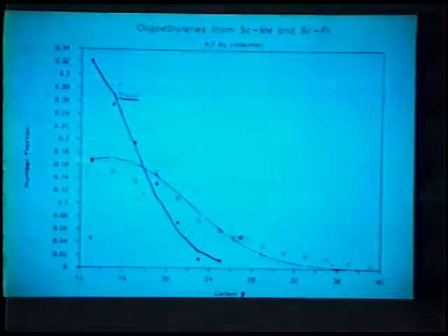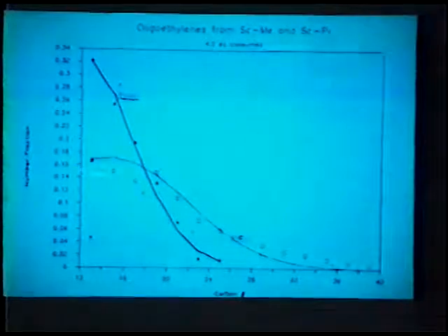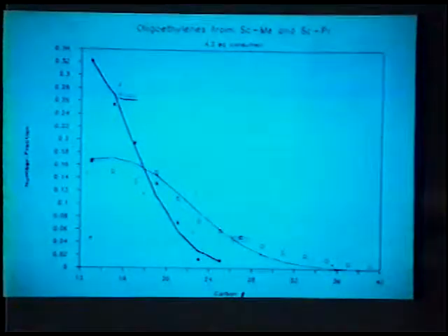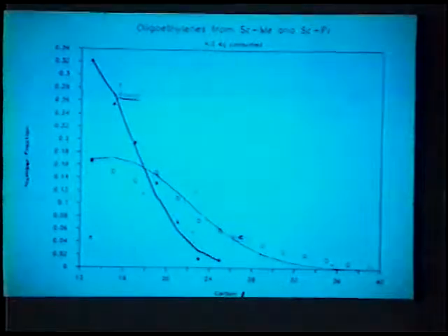Interestingly, with the methyl, where chain initiation is slower than propagation, we would expect a shift to higher molecular weights and a broadening of the oligoethylene distribution, as the system, which inserts early on, consumes a disproportionately large amount of the ethylene relative to starting material, so we get this broadened distribution.